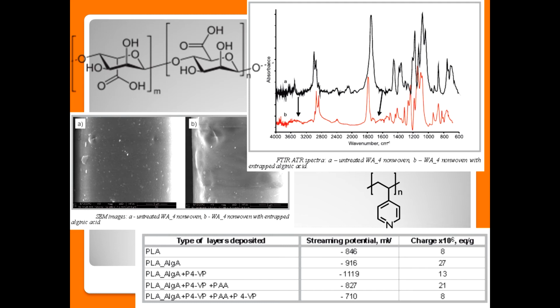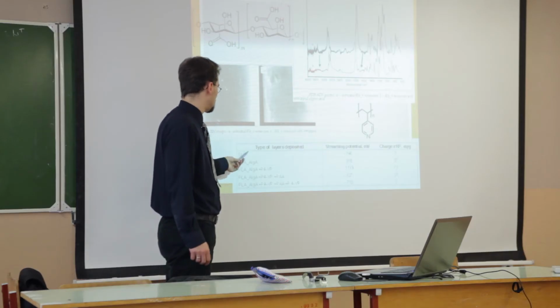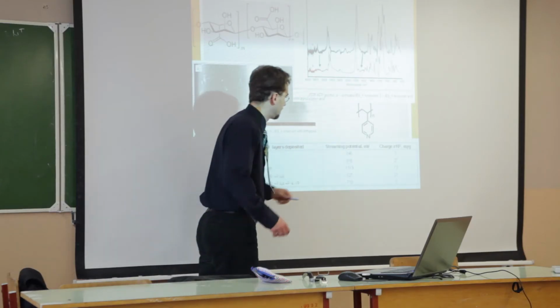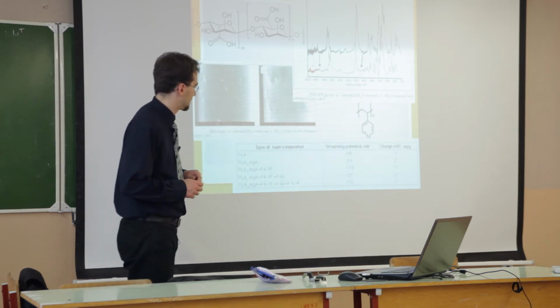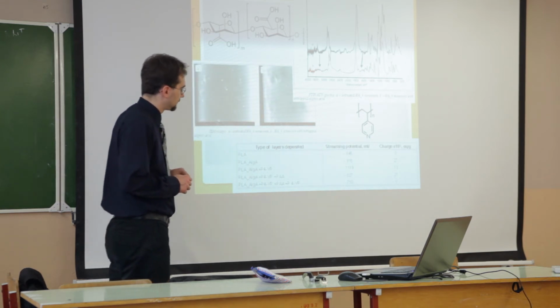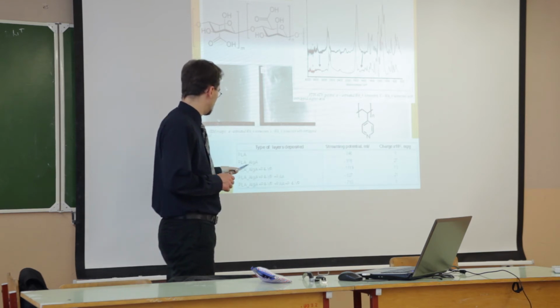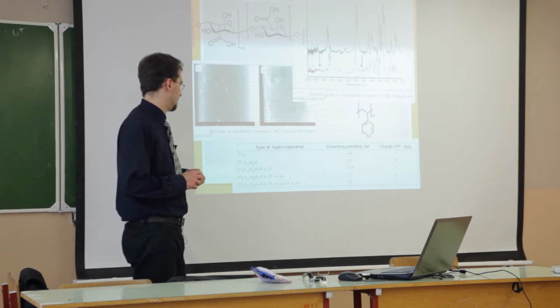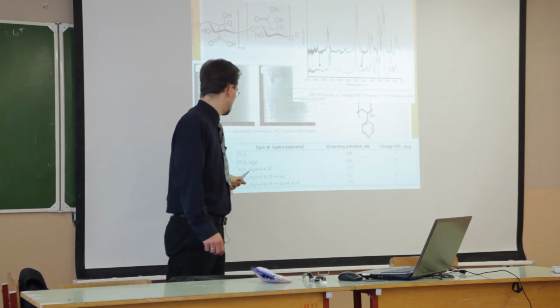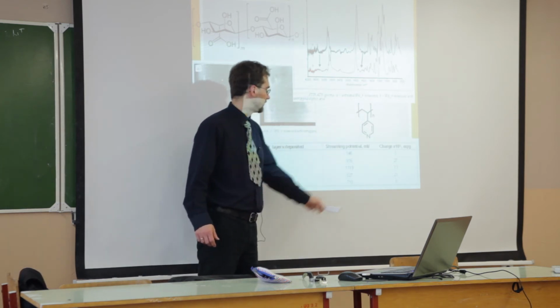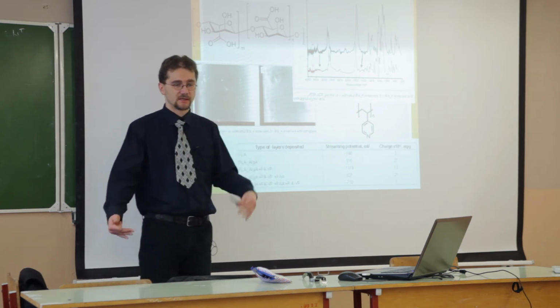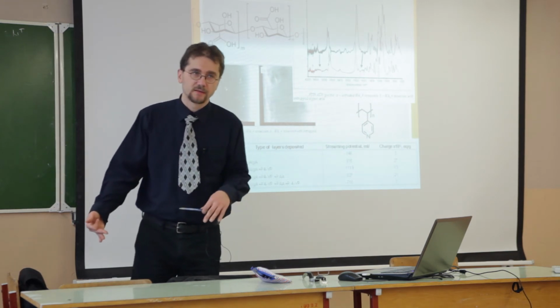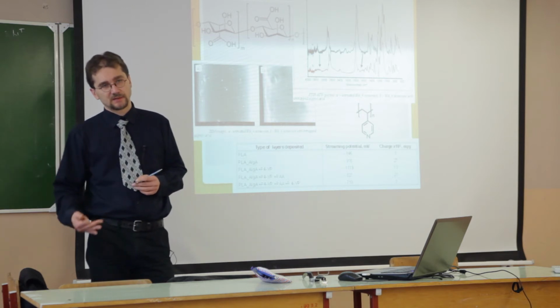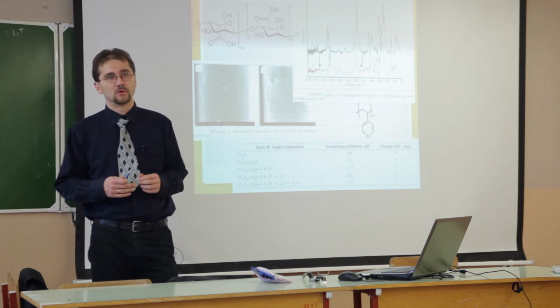Here you can see that changes in streaming potential depend on the final layer. For unmodified polylactide, it was minus 846 millivolts. With entrapped alginic acid, it was minus 916. Polyvinyl pyridine was the next layer, because our final expected effect was to have a multi-layered structure.